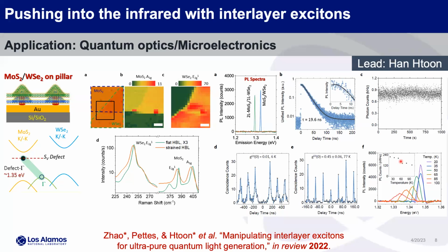That's just because you're making the difference between the defect energy level and the host level larger. You can see this is a pretty large area, but mainly because for this exciton, we don't have the recombination mechanism in one material because they're separated. This is a hybrid band, this gamma band, that pops up. Because they're separated, it just keeps the system much cleaner, and we're really happy about that as well. The energy scale here is still in the visible near infrared. It's not at 1550. It just has to do with the differences in the band edge, but it shows the principle works for interlayer excitons to increase the photon purity.